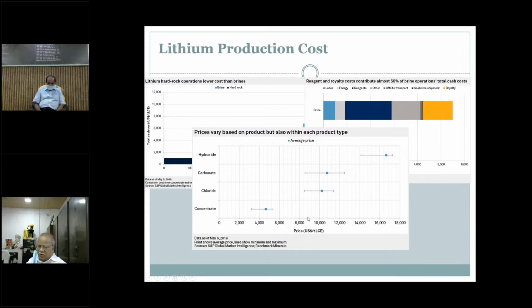And here is the cost of the concentrates we generate. Suppose the hydroxides will be fetching a market price of about $17,000 per ton of lithium carbonate equivalent, and the lithium carbonate will have a price of about $11,000, and chlorides about $10,200, something like that. The lithium concentrate after beneficiation, what we are going to generate, will be fetching about $5,000 per ton.